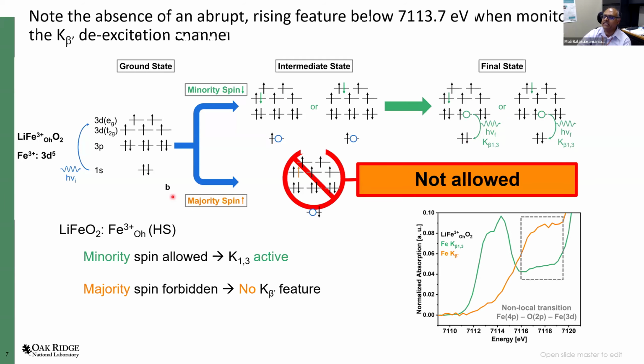Alternatively, one can consider taking the upspin electron and putting it into the D manifold. However, if you do that, what happens in this case, because all the 5 electrons are spin up, filling the available D states, you cannot put a spin up electron into this state. And so this transition where you try to take this 1s spin up electron and putting it into the D manifold will not be allowed.